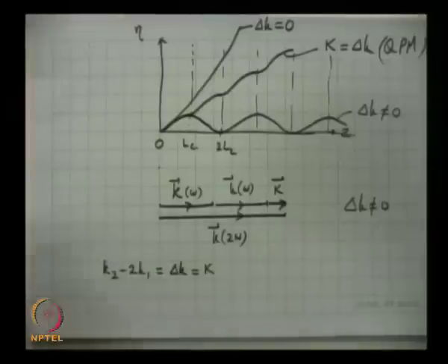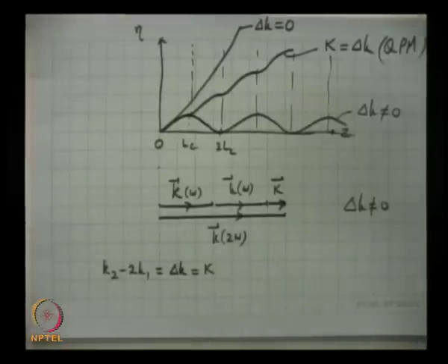Now, in gallium arsenide, to convert a 10.6 micron wavelength, what is the 10.6 micron wavelength? Which laser? Carbon dioxide laser. CO2 laser gives you 10.6 micron. So, I can do a second harmonic of 10.6 micron to get 5.3 micron. This period comes out to be about 110 microns or so. So, what people have done is I make gallium arsenide, and by orienting the crystal appropriately, I can change the direction of the nonlinear term, the value of the coefficient.